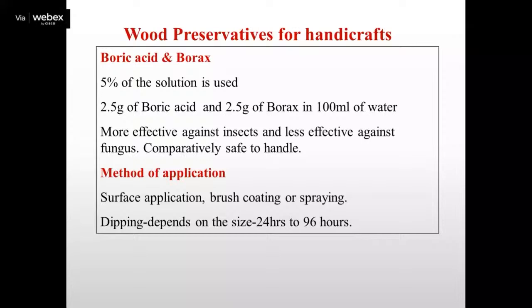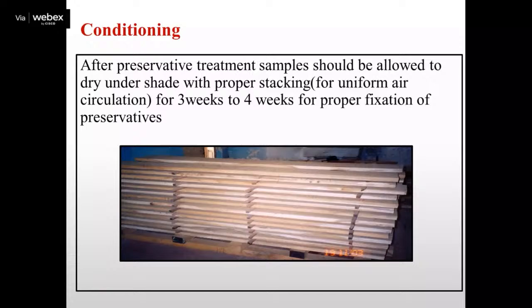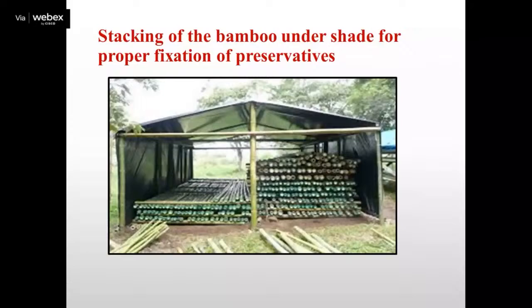So after all these treatment methods, conditioning is very, very important. Whether it is pressure treatment, dipping treatment or diffusion, after treatment it has to be conditioned properly. After preservative treatment, the sample should be allowed to dry under shade with a proper stacking method for uniform circulation of air for 3 to 4 weeks, depending on the size of the plank or the poles, for the proper fixation of the preservative chemicals inside the wood. So for stacking bamboos, this is the procedure: horizontal stacking is preferred.